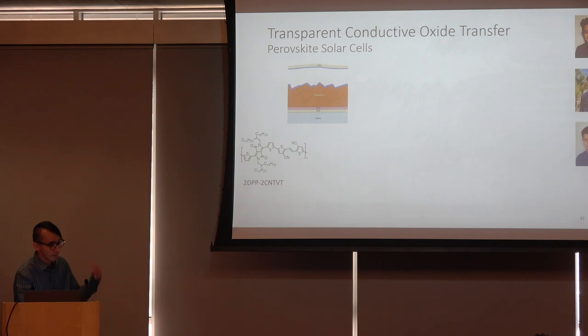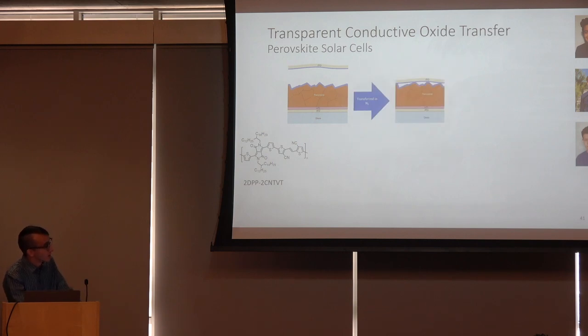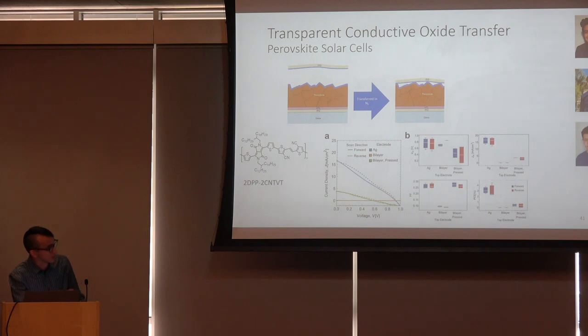And then we prepared bilayers of ITO and that same polymer, or we evaporated silver directly on the spin coated polymer. And so we either evaporated or we transferred. In the case where we transferred, what we think was happening is depicted by this image here. In these JV curves, you can see the silver in blue, and then the freshly transferred devices in orange here. And now that is a flat line, isn't it?